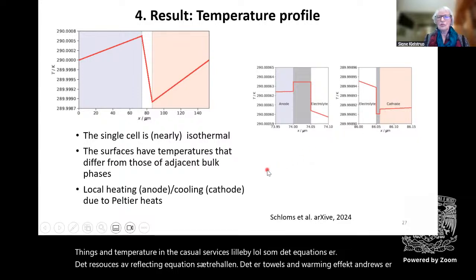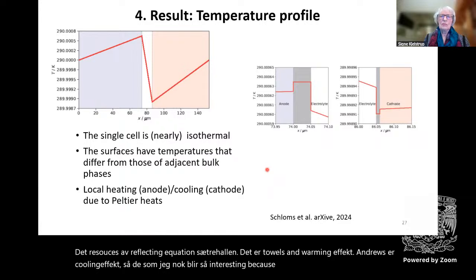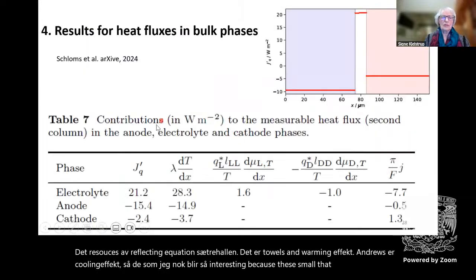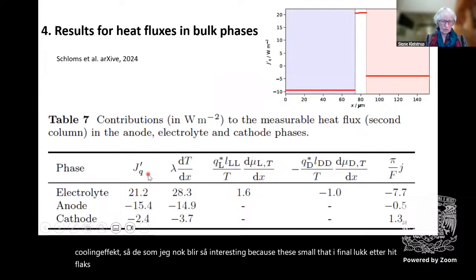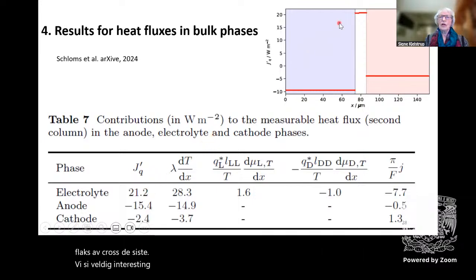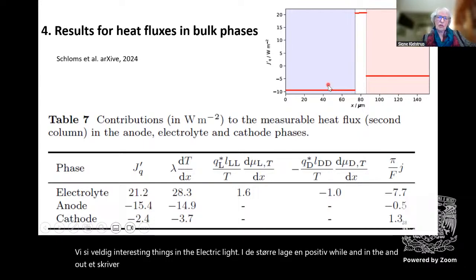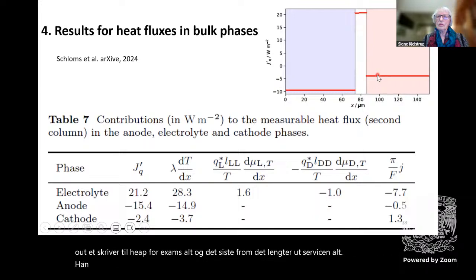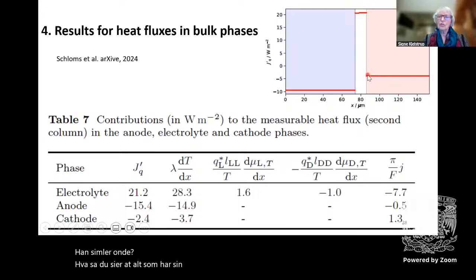So this may not be so interesting because it is small, but if we now look at the heat flux across the system, we see very interesting things. In the electrolyte, it is a large and positive value. And in the anode, it's clear that the heat flux goes out of the system from the electrode surface and out. And similar on the cathode side, it also has the same direction. It goes to the side which is cooled to compensate for that.